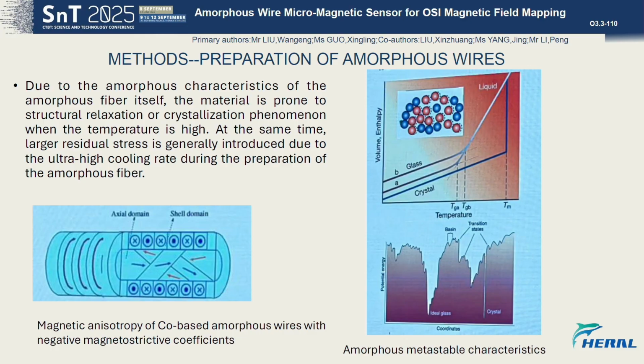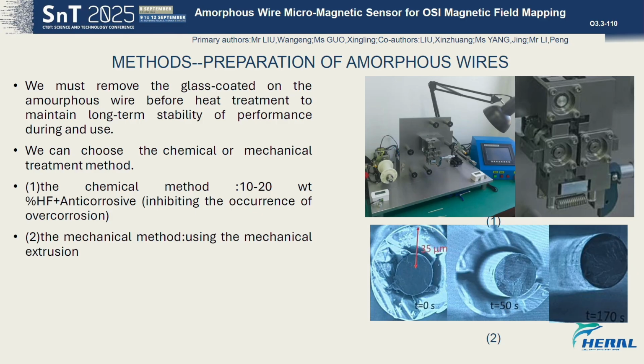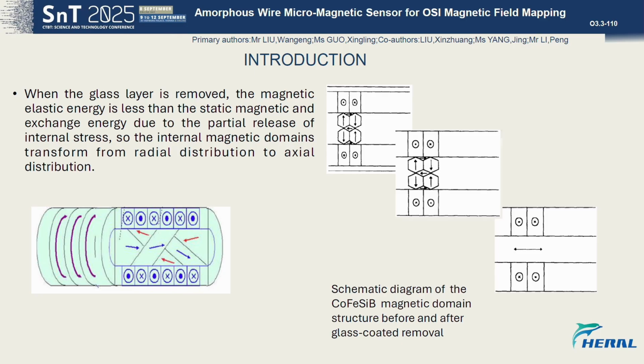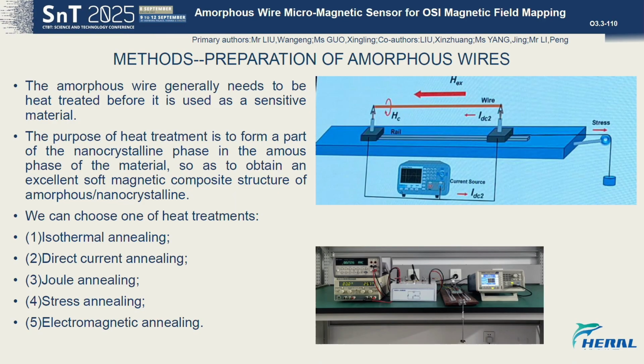At the same time, larger residual stress is generally introduced due to the high cooling rate during the preparation of the amorphous fiber. We must remove the glass coated on the amorphous wire before heat treatment to maintain long-term stability of performance during end use. We can choose the chemical or mechanical treatment method. When the glass layer is removed, the magnetic elastic energy is less than the static magnetic and exchange energy due to the partial release of internal stress. So the internal magnetic domains transfer from radial distribution to axial distribution. The amorphous wire generally needs to be heat treated before it is used as a sensitive material.